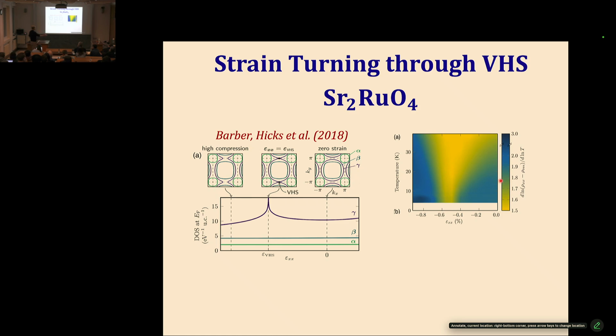So this is a plot of the log derivative of the resistivity. It's like showing a strain and temperature dependent exponent of the temperature dependence of the resistivity. And this value of the strain is where we expect the Van Hove singularity to occur. And we actually know what occurs there from the ARPES experiment. So you see this characteristic behavior on either side of this special point. You see blue. Blue is an exponent which is 2 or higher. But you see this fan-shaped regime where the exponent seems to deviate very strongly from 2. It's closer to 1.5.